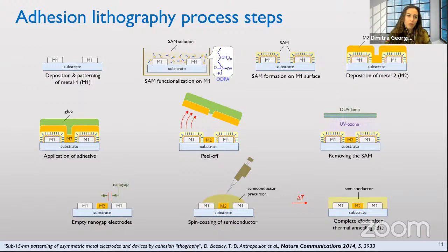The part of the second metal which is in contact with the SAM functionalized part of the first metal is being removed because the adhesion forces of that metal are weak. On the other hand, the part of the second metal which is in contact with the substrate where no SAM was present remains on the substrate because the adhesion forces between the second metal and the substrate are stronger. In this manner, we manage to have both metals sitting next to each other, and these are separated only by the SAM molecules, which we can easily get rid of by shining a UV ozone lamp on top of it or plasma ashing the substrates.